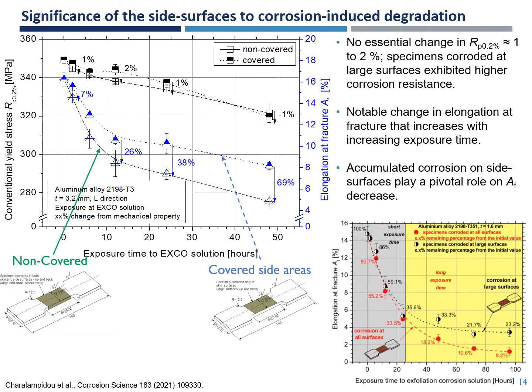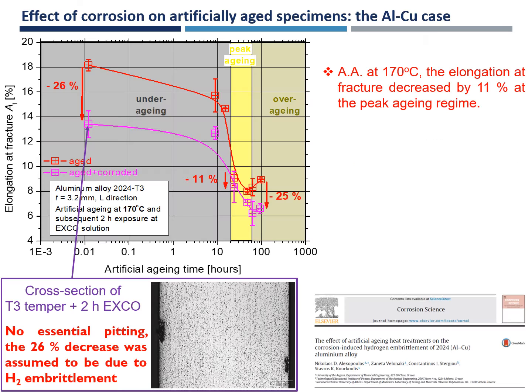These results are in accordance with the previous work of the authors, where accumulated corrosion on the side surfaces was found to play a pivotal role on the elongation fracture degrees of aluminum alloy 2198 in T351 condition. The effect of corrosion on artificially aged specimens of aluminum alloy 2024 was investigated in the previous work of the authors.